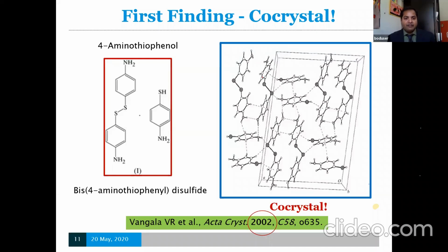the commercial source. When we kept it for normal storage for use, some of the 4-aminothiophenol may have undergone aerial oxidation. A small quantity of disulfide compound may have formed. We didn't realize it. We were trying to recrystallize 4-aminothiophenol, and what we observed in the crystal structure was a combination of a disulfide-containing compound with the 4-aminothiophenol, which we called a molecular complex at that time. We also refer to this as a co-crystal.